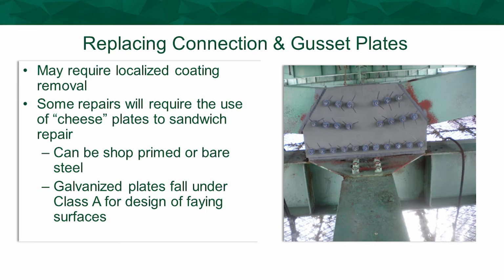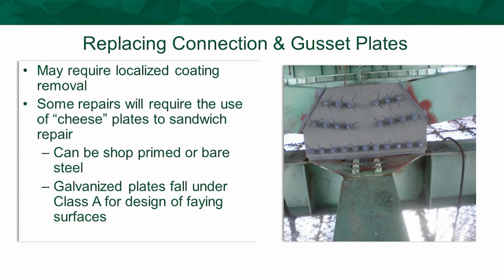Gusset plates, when you're replacing them, you want to make sure, again, you remove that localized coating system that may contain lead. When you're sandwiching plates, put them over deteriorated plates, you want to make sure that they're shop primed or bare steel. And if they're galvanized, just remember, galvanizing falls under the Class A for slip coefficient for faying surfaces.